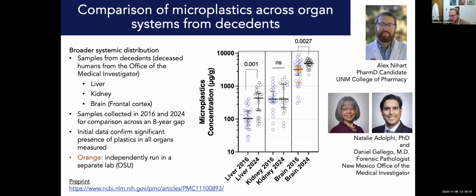And we did a head-to-head comparison of liver, kidney, and brain, specifically the frontal cortex. We also were able to get more recent decedent samples from about 2024. They were technically from November 2023 until January or February of 2024. But we were able to span essentially an 8-year gap. We ran the pyrolysis GC mass spec on the pellets derived from these samples, and we were able to show two things that were very compelling.